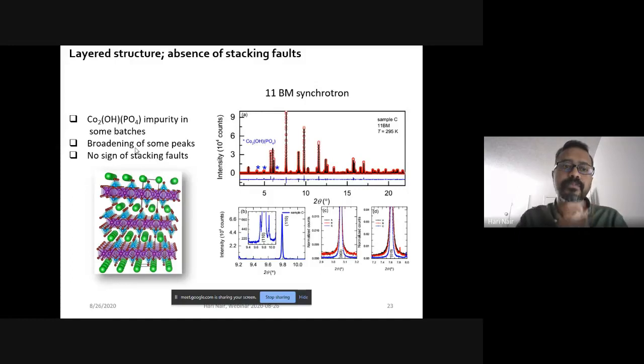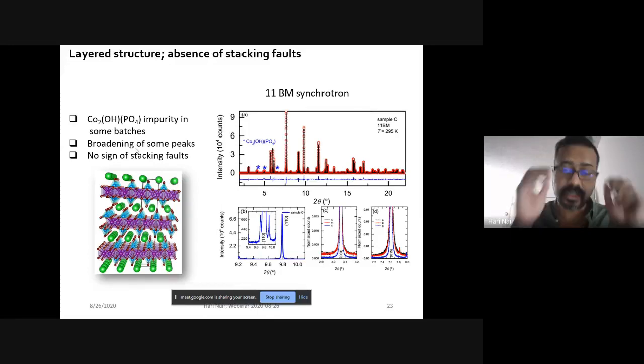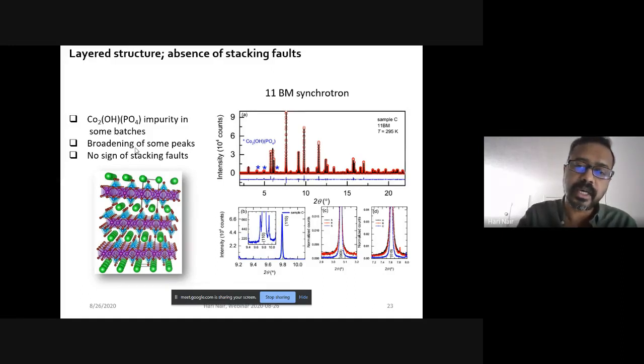Once that is done, we used high-resolution X-rays of smaller wavelength and higher energies, so that's synchrotron radiation, to study what kind of structural defects exist. What is the reason for that? The reason is that we want to know if these layers are perfectly flat or if they have some defects like stacking faults, some kind of buckling, where the layers are deformed and disordered. And indeed, there is some sort of slight indication. There is a broadening of the X-ray peak, as you can see on panels C and D. It means that there is some sort of disorder, but we could not quantify it.